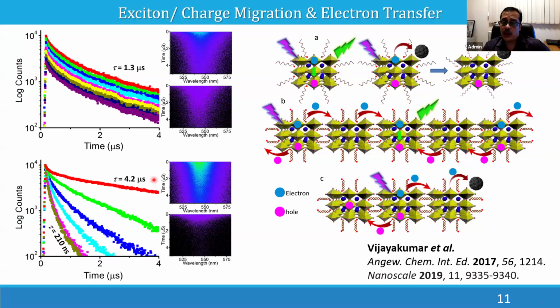We try to show this in a schematic representation. This is the normal solution state. When you excite, you are getting an emission. Okay, exciting at the blue wavelength, you are getting a green emission light. But when you add the C60, it quenches the emission. You are not getting any emission here. Okay. But in the case of the film, it is organized in a very self-assembled, beautiful manner. So when you excite, the excitons are formed and jump from one point to another point and finally give emission. And that time delay is reflected in the lifetime of the fluorescence.